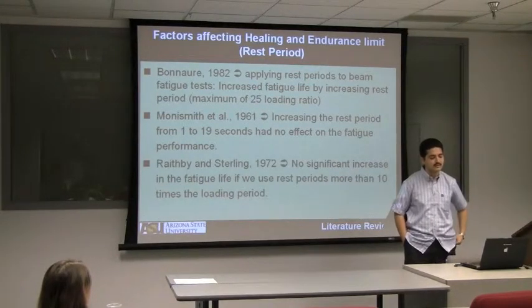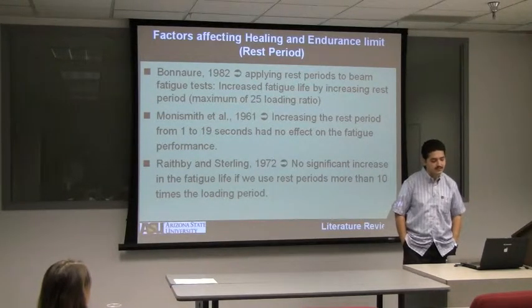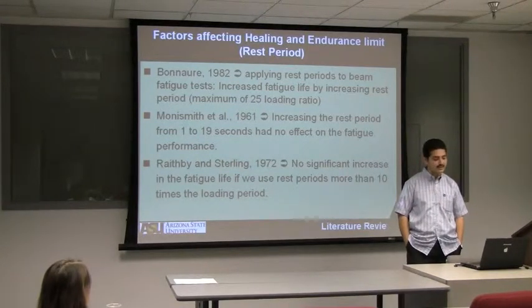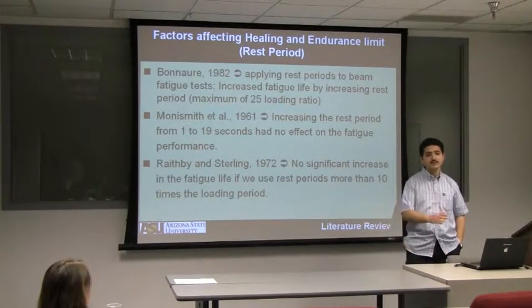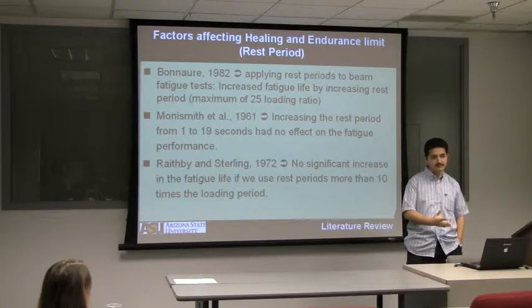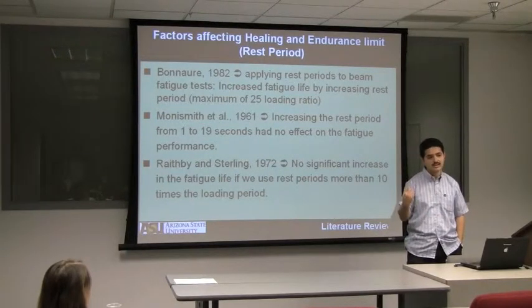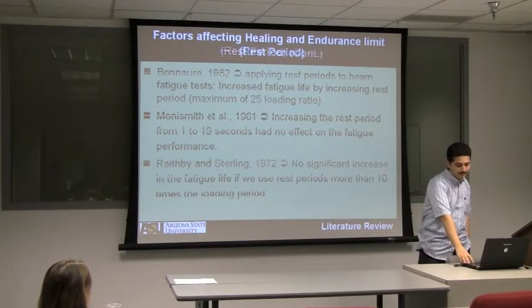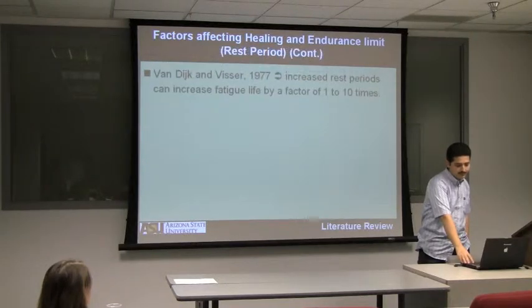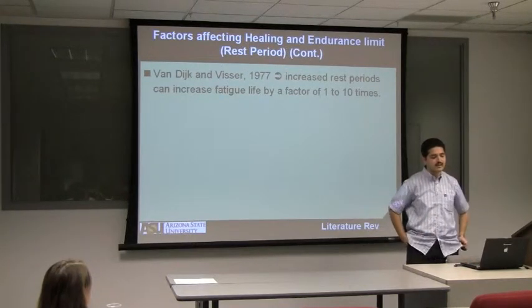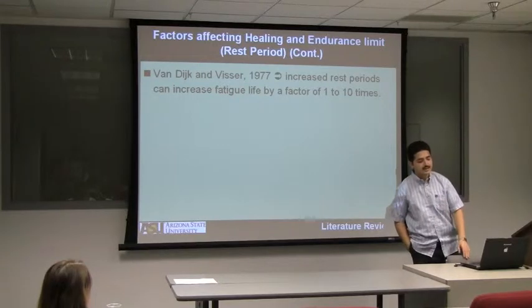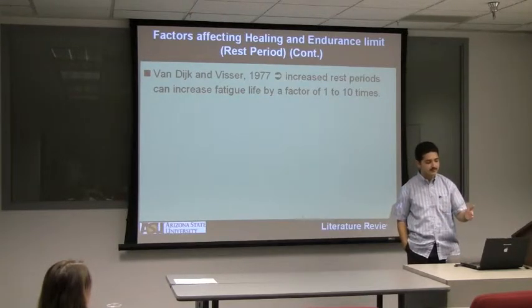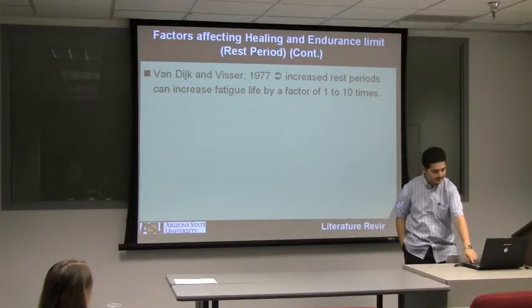Raithby and Sterling, also 1972, mentioned that there is no significant increase in the fatigue life if we use a rest period more than 10 times the loading period. So that means 1 second. If you apply 0.1 second loading, that means maximum 1 second you will gain full healing. Van Dijk, also 1977, mentioned that when he increased the rest period, the fatigue life can increase up to 10 times, from 1 to 10 times.